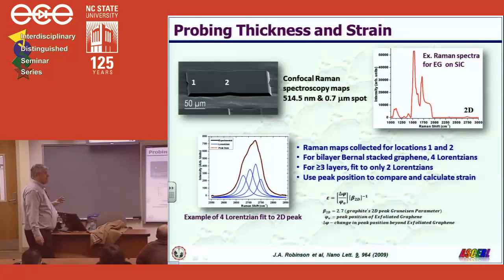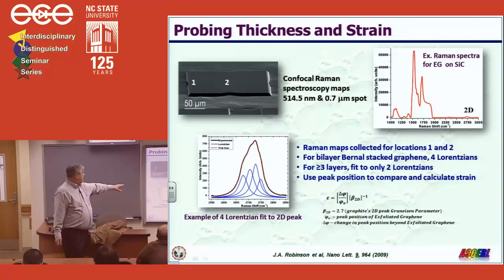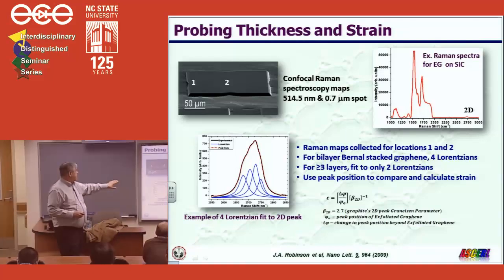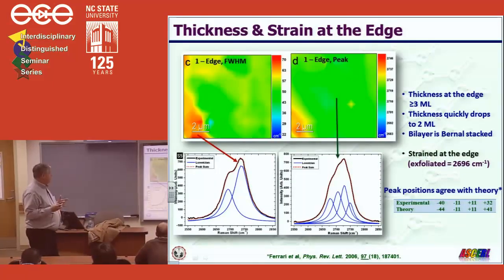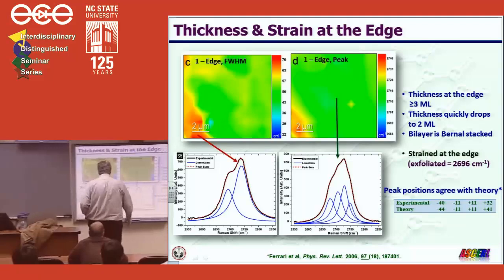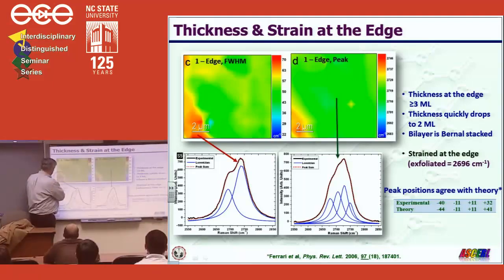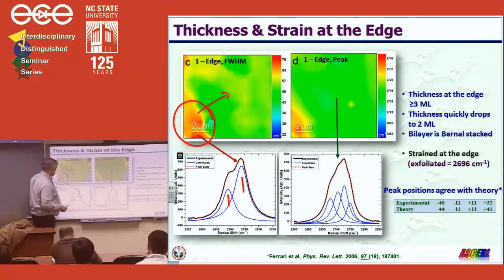Now let's use Raman spectroscopy. Let's take a look and see what kind of graphene we have there. Once again, we look at the particular 2D peak, and remember, if we have 2 layers of graphene, we have a sum of 4 Lorentzians, and then we can analyze the data based upon this. And here's an example of Raman taken near the edge of one of the mesas, one of the step-free flat mesas. Now, as we get right up to the edge, the full width at half maximum has a large value, and the Raman line shape is complex, consisting of 2 peaks. And that means it's 3 or more layers. When we get more into the center of the region, it consists of 4 peaks, and that's 2 layers.